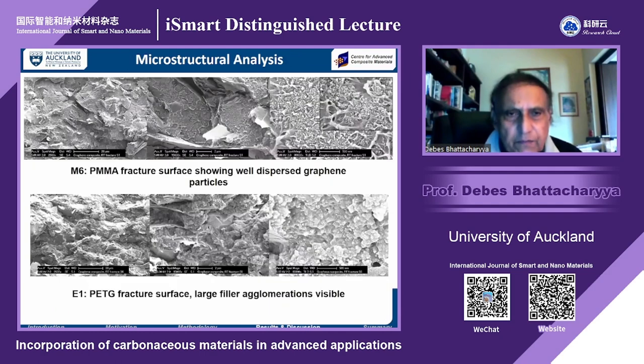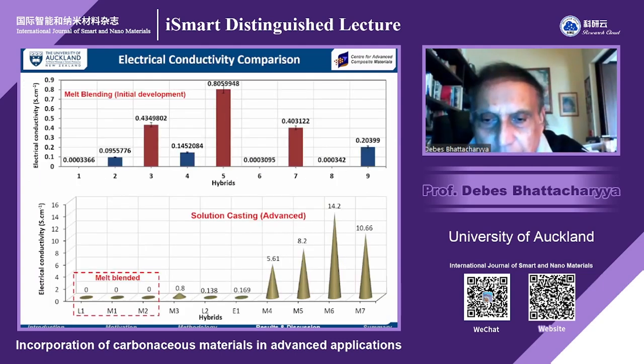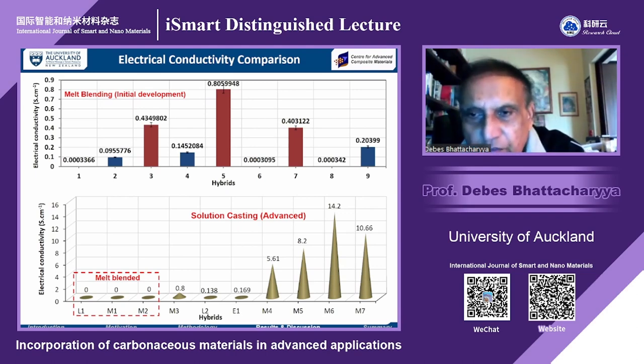So we figured out, from the scanning micrographs, that the PMMA fracture surface showed well dispersed graphene particles. That is why M6 gave better results. Whereas E1 had a fracture surface with large filler materials; there were agglomerations. So that is why the result was not that good. If we go back one, E1 is pretty low and M6 is very high.